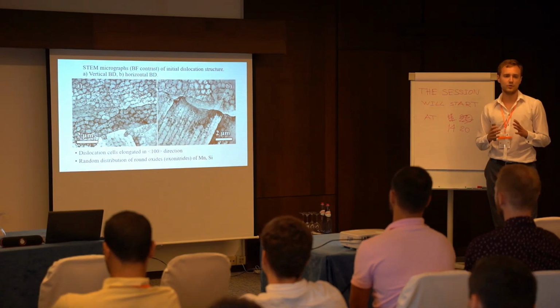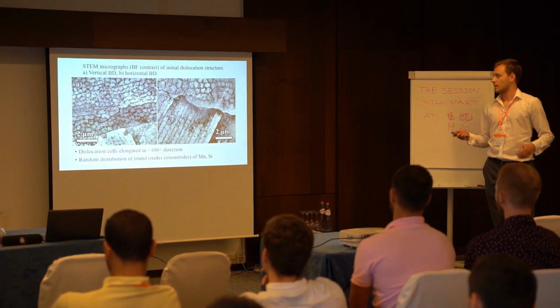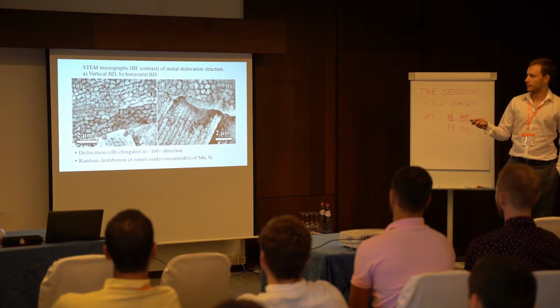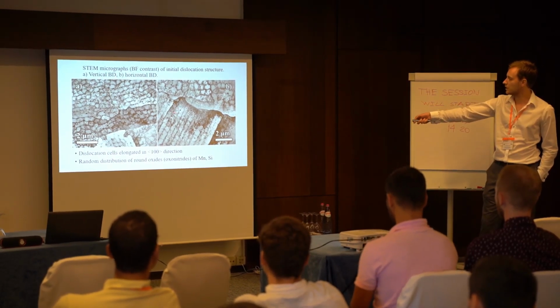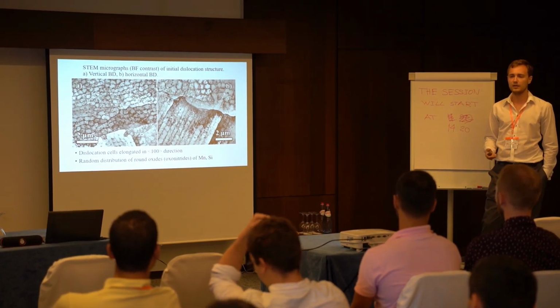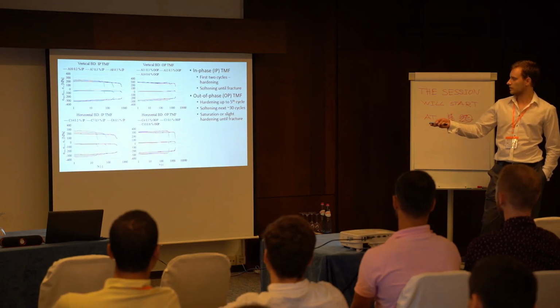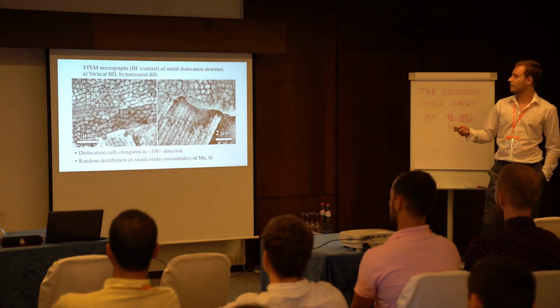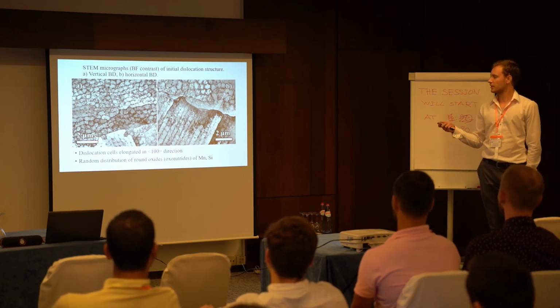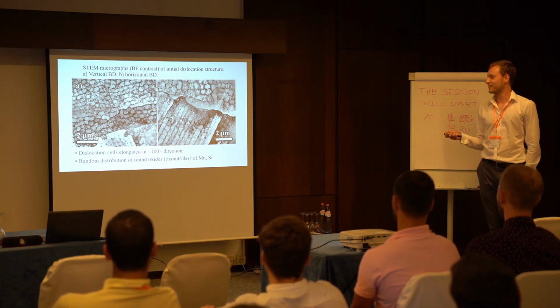We also saw dislocation arrangements in dislocation cells, which were elongated in one direction. The black dots you see here are oxides or oxynitrides rich in manganese and silicon, and the yellow ones. Interestingly, or rather importantly, the oxides were distributed randomly.